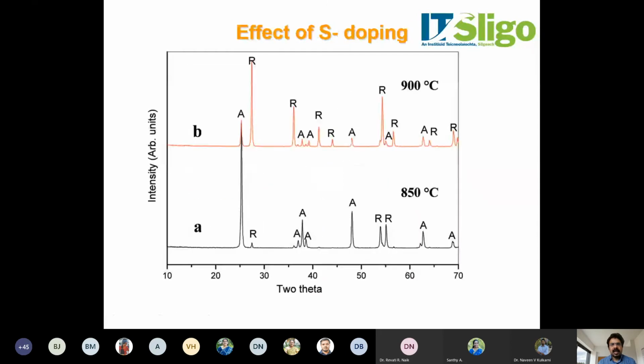You can see that we have traces of anatase phase even at a temperature of 900 degrees Celsius. This was the first set of reactions we have carried out, and after that we have carried out a number of different types of reactions and identified different types of dopants to keep the temperature stable up to 1000 degrees Celsius, and in some cases the temperature stability was above 1100 degrees Celsius. So that is exactly what we needed to coat these materials on ceramic tiles.